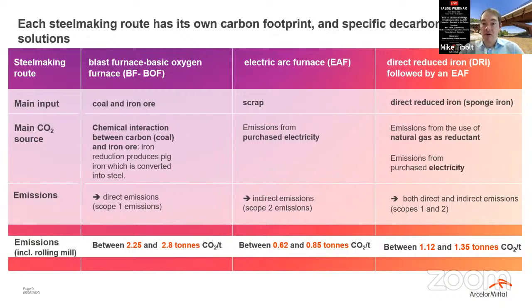And then we have the third route, which is the direct reduced iron route, followed by an electric arc furnace. Here we use iron ore that is reduced, at the beginning or for the time being, by natural gas to form what we call sponge iron, which is not a liquid pig iron anymore, but a solid material in the form of pellets that in a subsequent step will be melted in an electric arc furnace. And here we have as CO2 source a mix of two emissions, from the reduction and from the purchased electricity for the electric arc furnace. Here the emissions lie between 1.12 and 1.35 tons of CO2 per ton of steel produced.